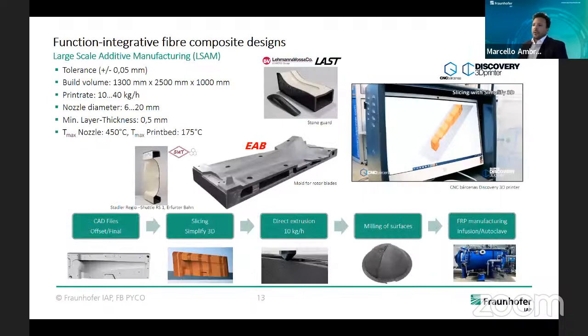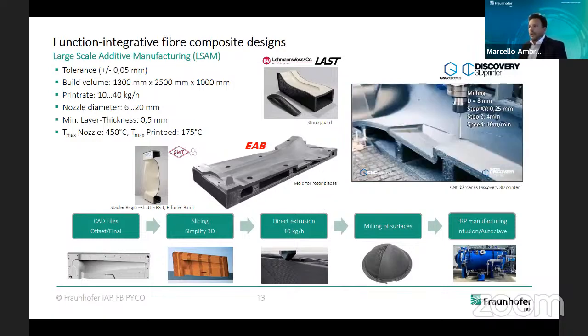Here just a short explanation of how this printing system works. We have a large-scale additive manufacturing center. We can extrusion print up to 1.3 by 2.5 by 1 meter. So it's quite a high volume with a maximum print rate of 40 kilos per hour. And we printed this tool, which you can see here in the middle, for the rotor blade in 7 hours.